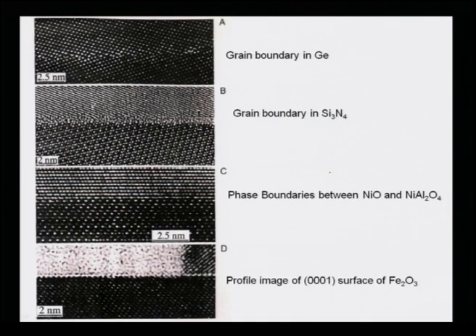What you can see here are all the black and white dots of atoms, where you do not know which one is what. But you can see the antiphase domain boundaries marked by these white circles. Also, you can see a huge number of distortions in the picture. Next one is taken from a set of pictures by many authors, some of us included. So, we can actually image a grain boundary of germanium. You can clearly see it consisting of dislocations at different intervals. It is a low angle grain boundary consisting of a parallel set of dislocations.